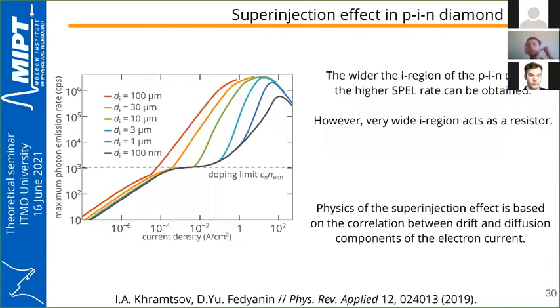We have also studied the superinjection effect and found that wider I regions of the PIN diode result in a higher SPEL rate. However, very wide I regions act as a resistor, and to obtain the same brightness of the color center at a wider I region, one should apply high bias voltages that might not be suitable for on-chip technologies. We also found that the physics of the superinjection effect is based on the correlation between the drift and diffusion components of the electron current.